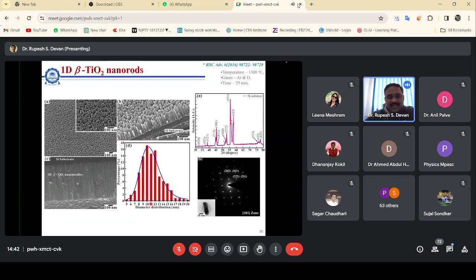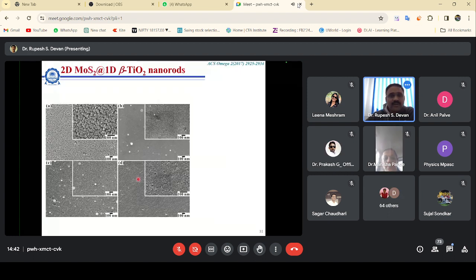To get the anatase phase, even though a dimension less than 11 nanometer is required, the hydroxyl group plays a major role. Suppose during synthesis your hydroxyl group exists, then definitely you will get an anatase phase. So we avoided the existence of hydroxyl groups here, and we prepared this at a very high temperature, close to 1300 degrees Celsius. And that's the reason the anatase phase has not formed.